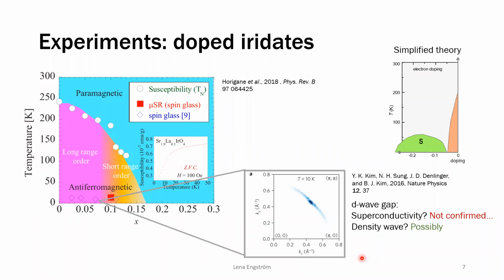Is that clear? Because from the Kim paper that has this plot, they suggest it's superconductivity just based on the similarity with the cuprate model and the crystal structure, right? So can you maybe clarify which experiments suggest that with this doping? Because the doping for that plot is special, right? It's this in situ potassium doping. It's not your usual doping. So have people done this experiment with this type of doping in a broader regime? I'm trying to understand why it's density wave versus superconductivity.